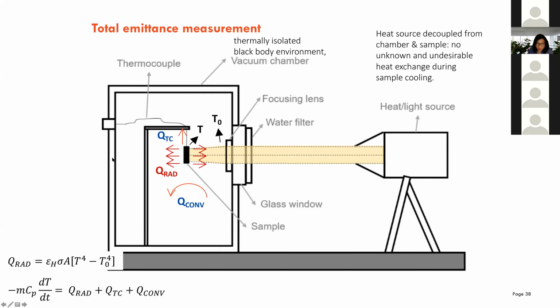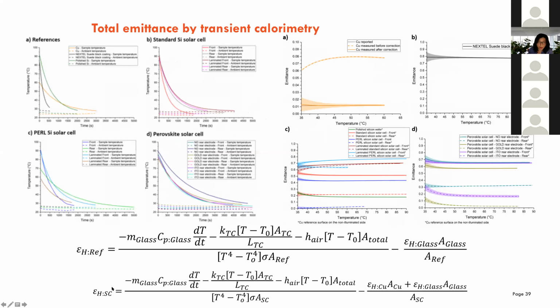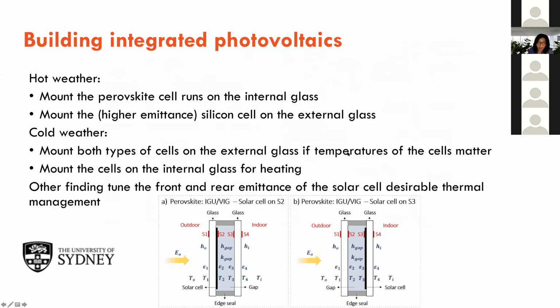So we have this setup, and using this principle, we're able to calculate the emittance of the solar cell using a known reference, for example, copper or a black material with known emittance, measure the temperature change curve, and we can work out the emittance of the cells. We plug that into the formula in the heat transfer equations, and we managed to find out the temperature of the solar cell as well as the temperature of the glass, whether it's on the outdoor pane or indoor pane.